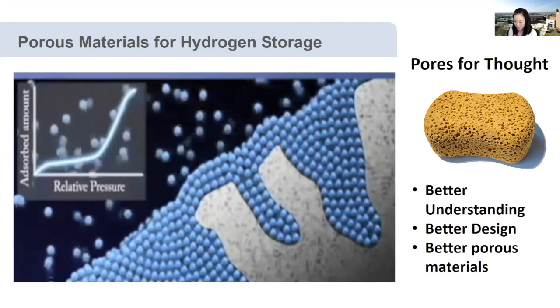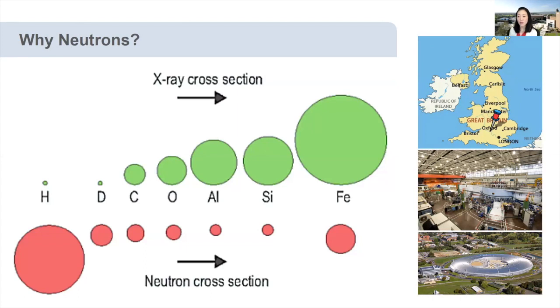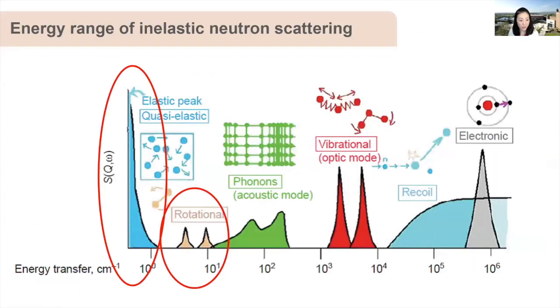So hydrogen is lightweight, an invisible gas, and is insensitive to lab-based techniques, for example, X-ray diffraction. If you see this figure, hydrogen has the smallest X-ray cross-section. On the other hand, the neutron cross-section of hydrogen is the largest among all the elements. And the neutron can deeply penetrate everything, the cryostat, sample cell, sample itself, and directly probe hydrogen inside the pores. So making neutron an ideal tool for studying hydrogen storage materials.